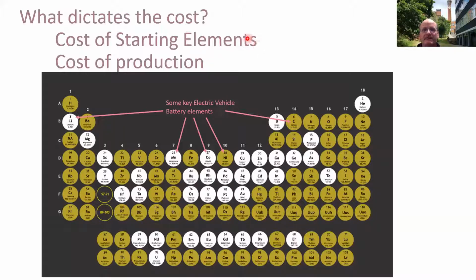So the key thing that's actually driving cost at the moment is probably the starting cost of the materials. If we look at the materials that are in there, obviously lithium, we've got cobalt. Because cobalt's expensive, we're essentially replacing a lot of the cobalt with nickel and manganese. And then we've got our graphites as the other electrode. In particular, the cost of things like cobalt, nickel, and getting a bit more costly lithium is driving the overall cost of the cell. So gains that we're making by improving production are being partially taken out by increasing cost of the elements.